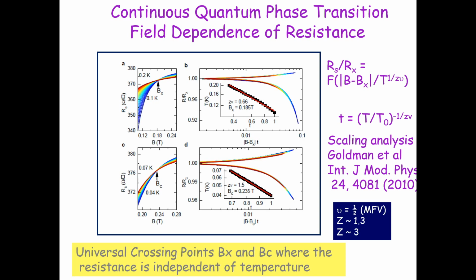And I can do a plot of log of t versus log of this small t, and it gives me the exponent zν, and this gives me the critical field Bx. So this is what happens at the first transition, happening at a slightly higher temperature. And at very low temperature, the second one, again you can do a data collapse. Everything looks similar except the exponents are very different. Here it is 0.66 and here it is 1.5.